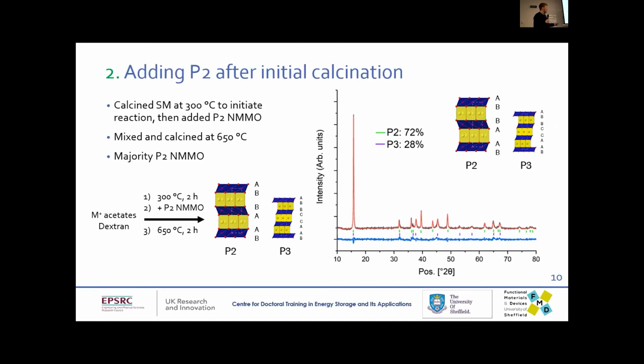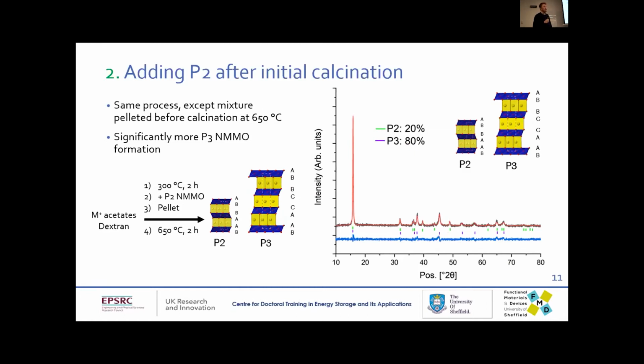The reason I think it's majority P2 in this XRD is because it shows up slightly differently. The intensity counts will be slightly different in the XRD. So if I mix two separately made powders of P3 and P2 in a 50-50 ratio by mass, it will have about this same ratio when I try and work it out using Rietveld refinements. However, if I do the same, except before calcining it, I pellet this powder and force all the different particles together, it changes the ratio of what we get out in the product. So we get this majority P3 phase.